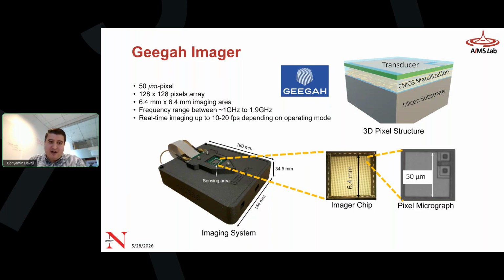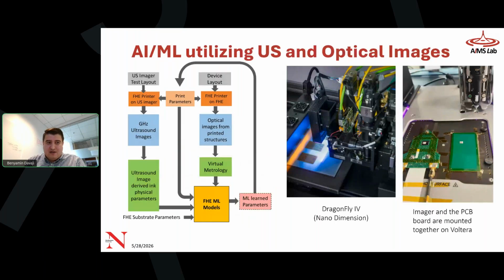And they operate at very, very high speeds, high frequencies, around 2 gigahertz. Compared to the medical ultrasound, this is 100 times higher frequencies. And they can measure the differences in acoustic impedance or differences in material properties. So we designed a closed loop operation, and I'm going to show some examples of some Dragonfly printed devices that were measured, and also some Voltera measurement with extrusion printing and inkjet.